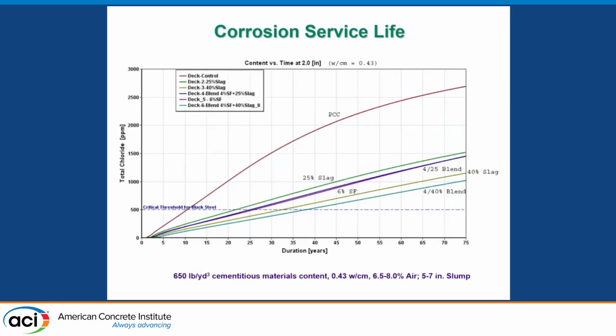And then just kind of summarizing some things up here, I don't want to take too much time. We actually ran this corrosion service life of chloride content versus time, and we can see that over the course of time, the critical threshold of black steel is here, but we can look at our duration and service life and see that obviously my deck blend, 4% silica fume, 40% slag, is where they kind of leveled out. Very similar here at 6% silica fume and a 4 and 25 blend. So while silica fume can be expensive, if we can reduce the amount of silica fume but supplement that with slag cement, it can be quite economical.